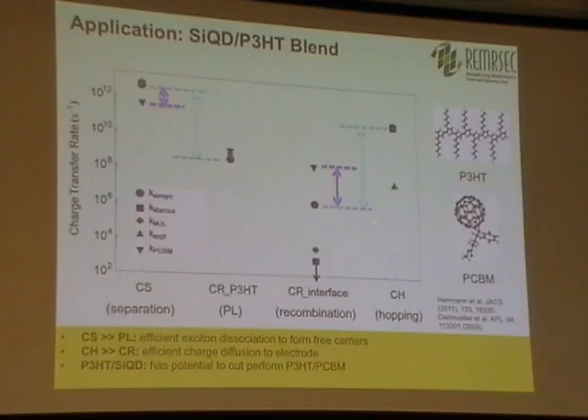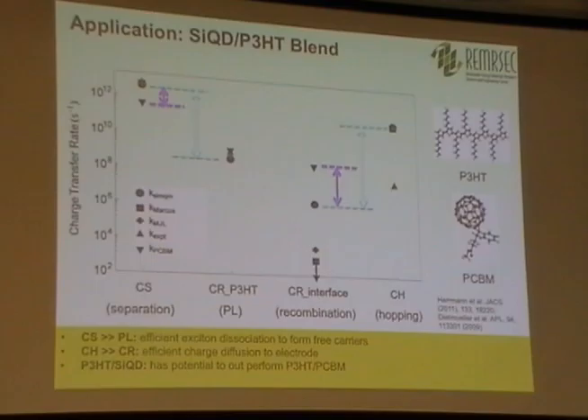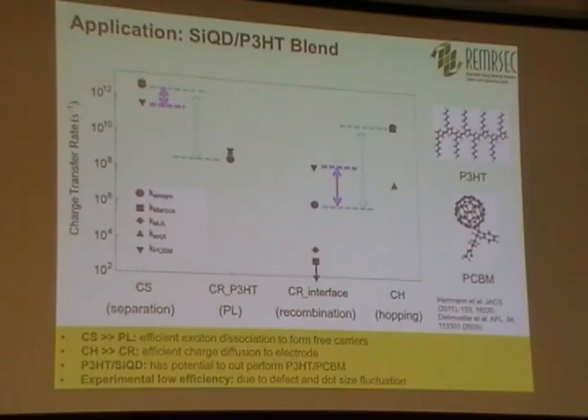The recombination rate associated with PCBM versus the silicon quantum dot: the recombination rate for the silicon quantum dot is much slower than for PCBM. That's good news too. In both comparison cases, the silicon quantum dot gives superior results. However, there is one point where experiment differs from theory — the charge hopping. The measured electron hopping rate is orders of magnitude slower than predicted. We think that's because of defects in the system and fluctuations in dot size that Matt talked about, causing the mobility to be lower. Theoretically we're assuming an idealized system, and we really need to account for defects and geometry fluctuations.